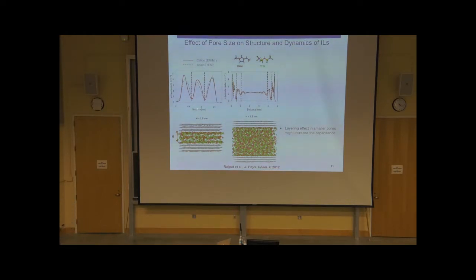So in smaller pores, what we observed is that there's a significant layering effect because of strong interaction between the pore walls and the ionic liquids. So the density near the surface is high and they form very well-defined layers inside the pores. As we move to the larger pores, we still have higher density close to the surface, but in the center of the pore, it's more like a bulk region. And we observe that this layering effect is one of the main reasons why the capacitance is really high in smaller pores as compared to larger pores.